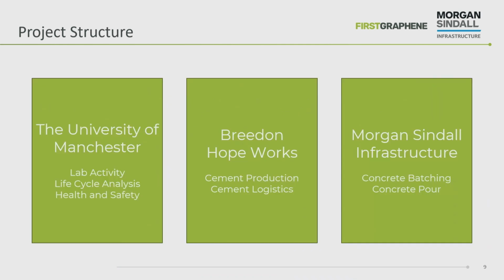So we worked with the University of Manchester. They were looking after the lab activity. They were looking at the CO2 footprint of the cement and of the graphene and of the mixture. They were looking at the health and safety aspects of having a nanomaterial in the cement, something that's not been done before. Breedon were in charge of the cement production and the logistics and getting it to the batching site, and then Morgan Sindall were in charge of looking after the concrete batching and pouring it into the slab, which you'll see some images of.